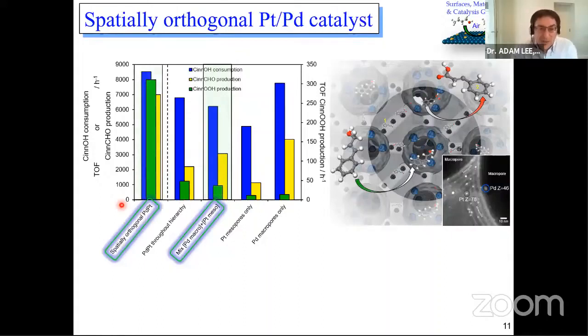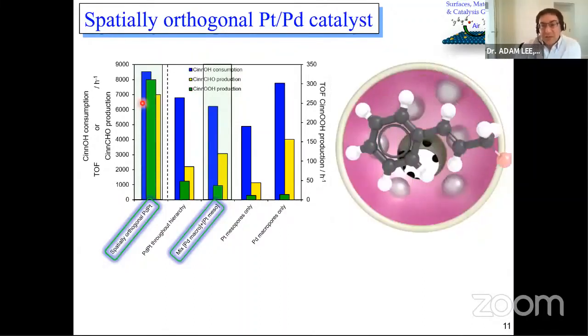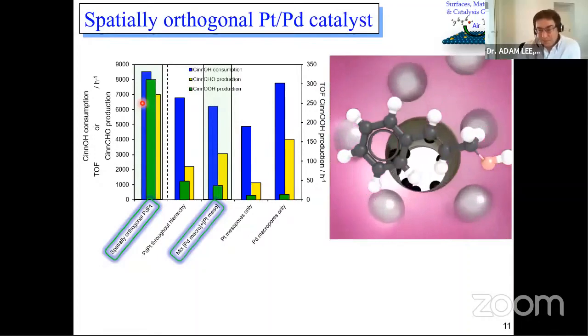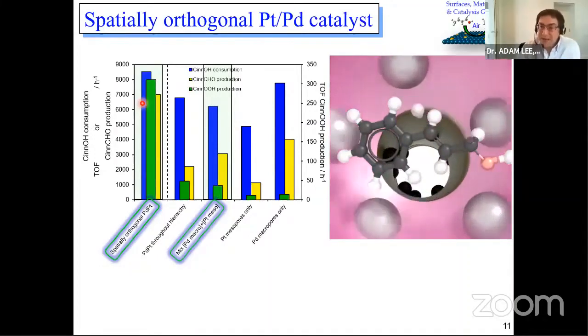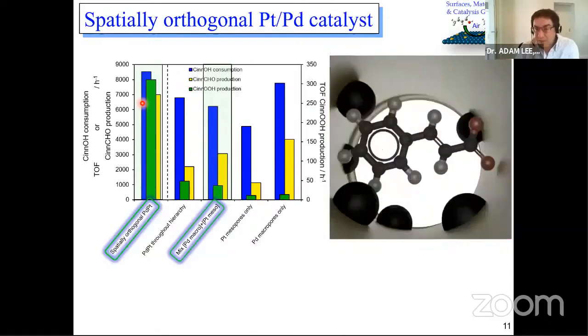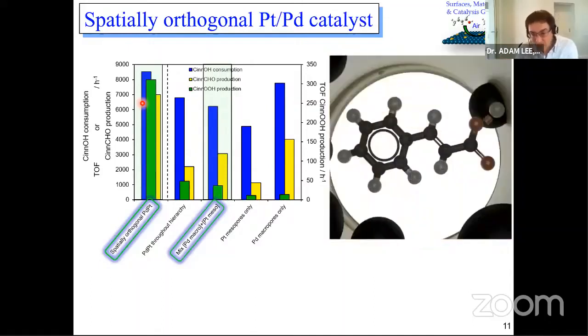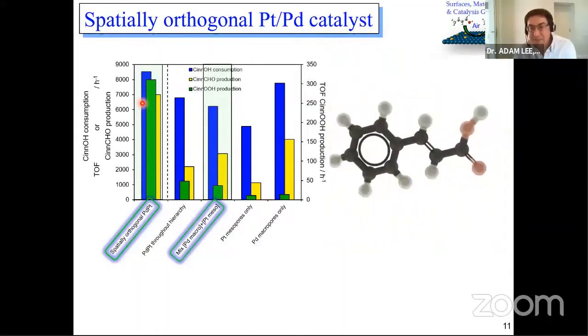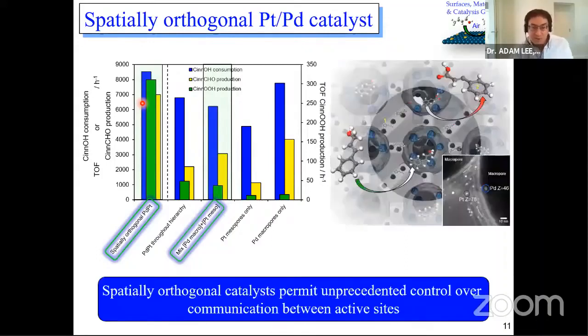By comparison, the spatial orthogonal catalyst is extremely good at making the acid. It does the cascade. It can do both steps of the reaction. So just to visualize that, the alcohol molecule enters the big pores, undergoes the first transformation to an aldehyde over palladium, diffuses into the smaller pores, where it undergoes a second oxidation step to form the acid. So there we go. We've got a spatial orthogonal catalyst that allows us very precise control over the sequence and the communication between these two active sites.